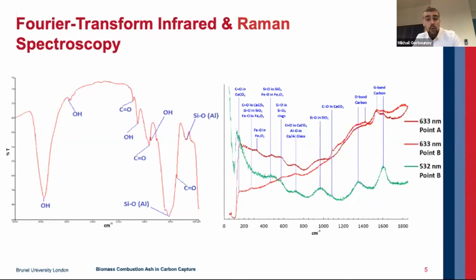Some bands around the smaller wave numbers are believed to be representative of iron oxides, and these chemical compounds have been identified via XRD analysis, and nevertheless, the Raman has confirmed those assumptions. Another point to mention is that the Raman spectroscopy was conducted at different points in order to cover a wider scope of the material, but the results from them are largely the same.